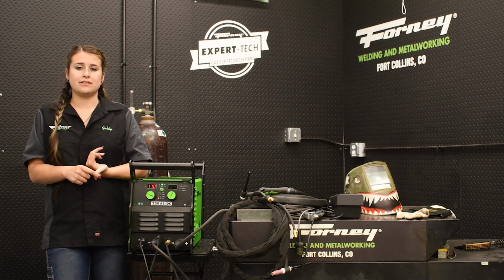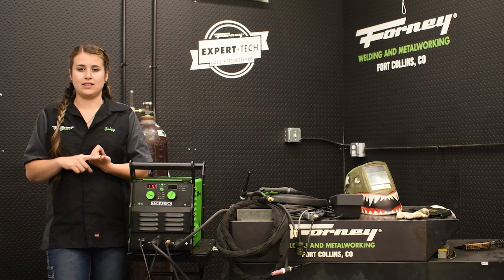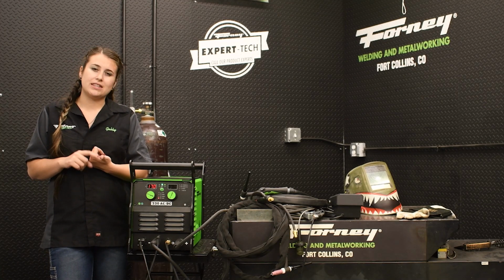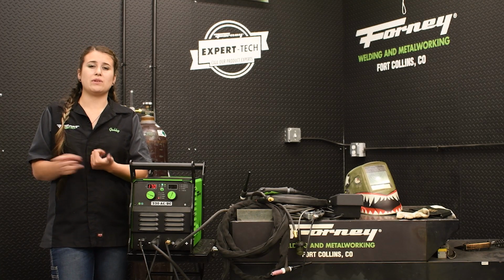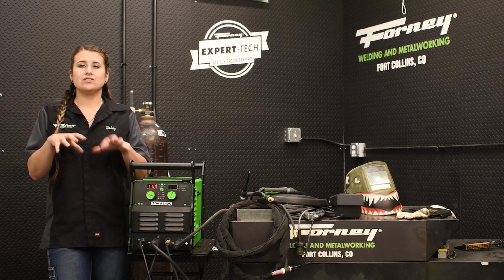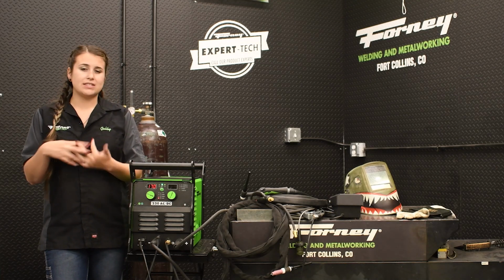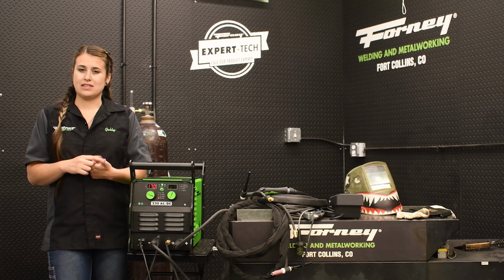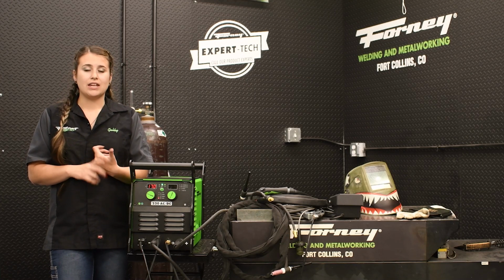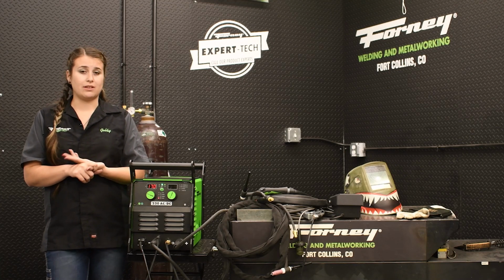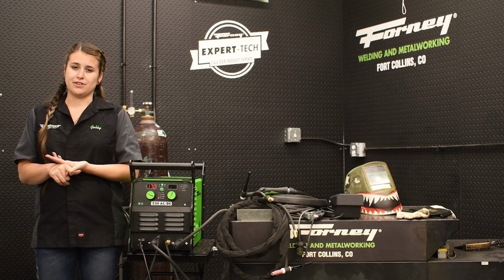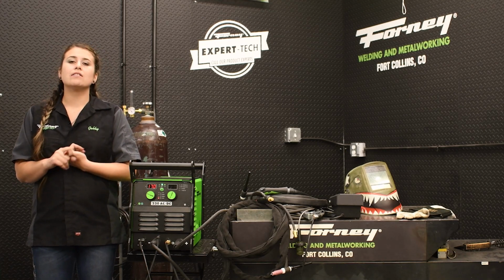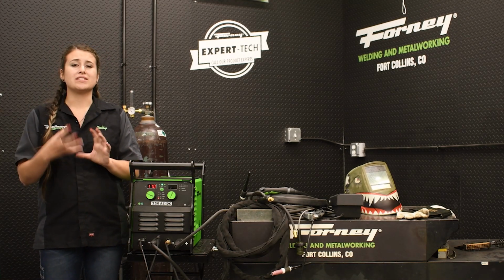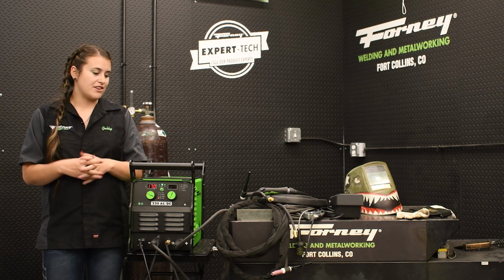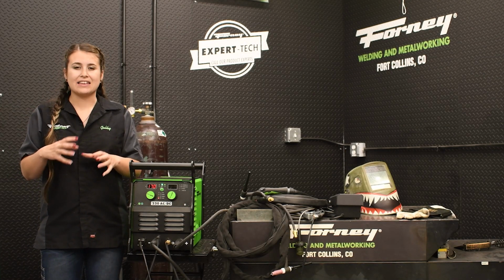One thing to keep in mind is when you are welding aluminum, you do not want to clean that material with anything that has steel in it. If you clean that material with anything with steel in it, it is going to impregnate the steel into the aluminum. And once that has happened, you cannot get that aluminum clean again, and you're going to have to figure something else out for your material that you're going to use. If you try to weld on aluminum that is impregnated with steel, it is actually going to be very dirty. It's going to be black and sooty.